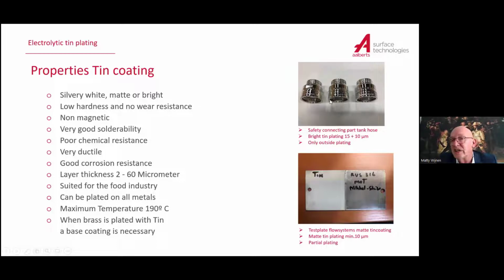Where it's used, on the right side, you see we use it for a connecting part of a tank hose. It's our parts which are only tin on the outside. Inside, the part is aluminium, and the inside is kept free. It's used for when you tank at the gas station and you leave your tank hose in your car and drive away, this is a safety part which will make sure that the hose doesn't take your tank with it, but is disconnected. And under that, you see a tin plate, which is matte tin plated, and that's used for flow systems. Also partial plating.